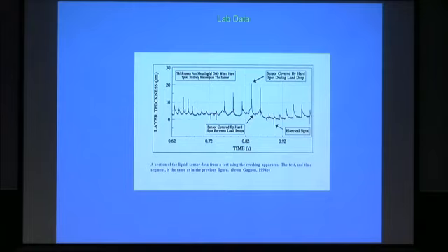Here I've called it liquid thickness, but really it's the amount of liquid that the sensor detected. On average, during the ascending parts of the sawtooth load pattern, it was sensing a certain amount of liquid. And then during the load drops, which caused the pressure spikes, there was much more liquid present, and that's what these spikes here correspond to.